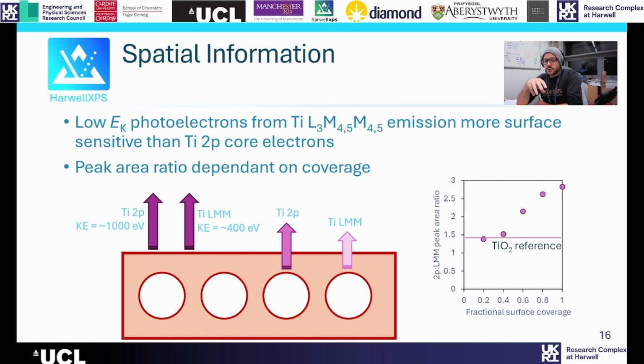Now, if we think about the pore structure of our material here, we're going to have contributions from titanium atoms that are located on the outer surface of our material, but also buried within our material, coating the walls of those pores within the material. Now, the titanium 2p photoelectrons will have enough kinetic energy to give us a signal from the walls of these pores, whereas our Auger electrons are unlikely to be able to escape to the outer surface and be detected in our experiment before they're attenuated.